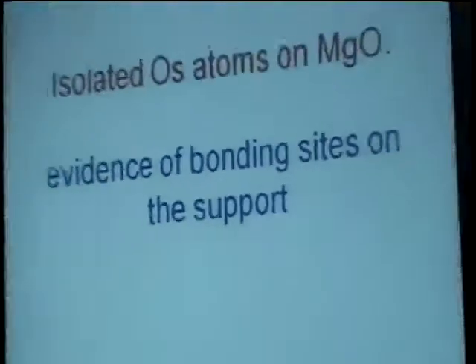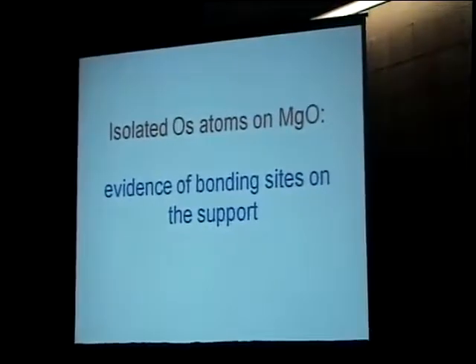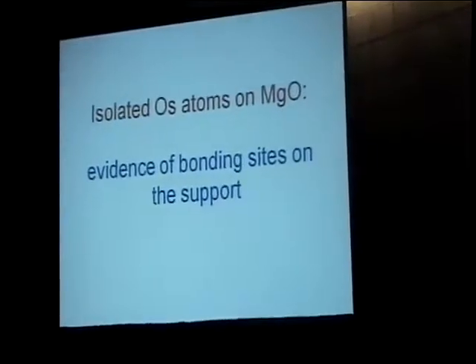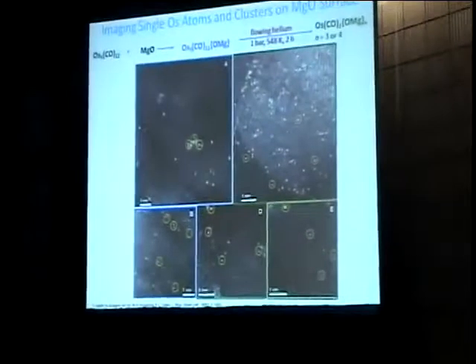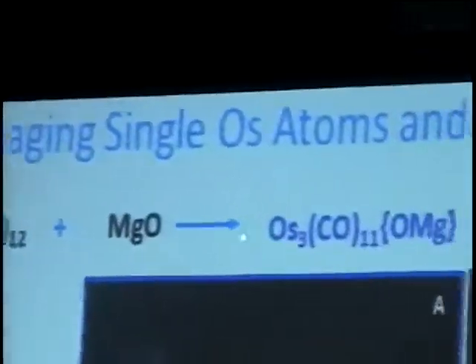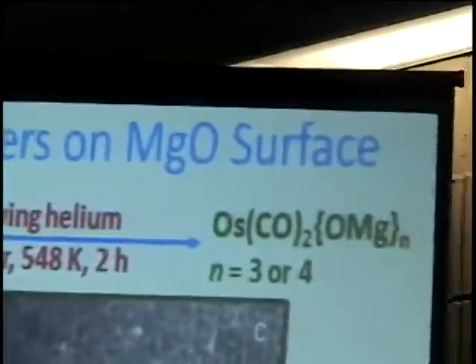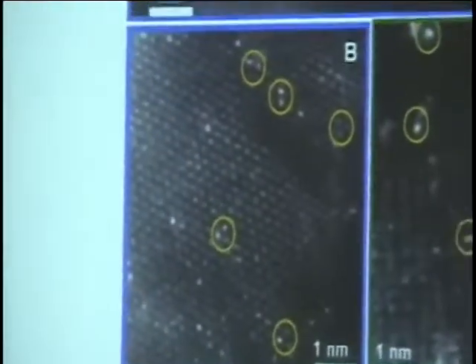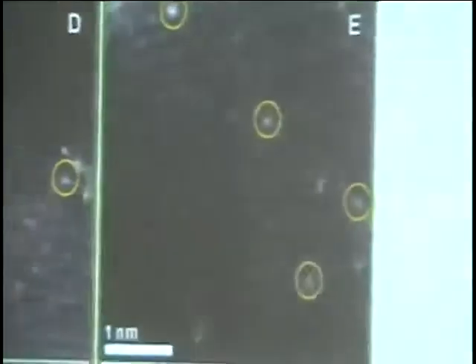Okay, so let's now start marching through a set of samples formed from the parent triosmium. So we're going to make isolated osmium atoms on the MgO from the triosmium. So this is the oxidative fragmentation reaction. We do the adsorption, we get the triangle with one fewer carbonyls. I'm not showing you the spectra, but they bear this out. And then this oxidative treatment leads to the fragmentation, and I'll show you some spectra a little later, but not now, whereby we break the triangle into individual osmiums. So here are the triangles, and here, for example, are the isolated single metal atoms. So we're doing the oxidative fragmentation.